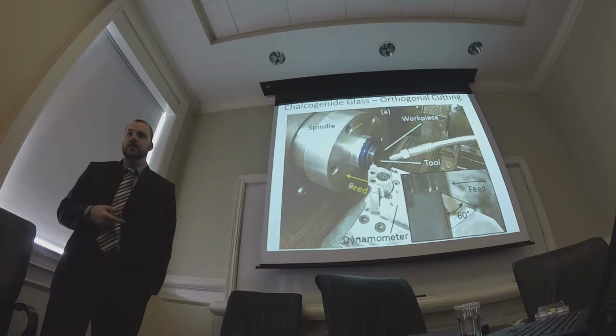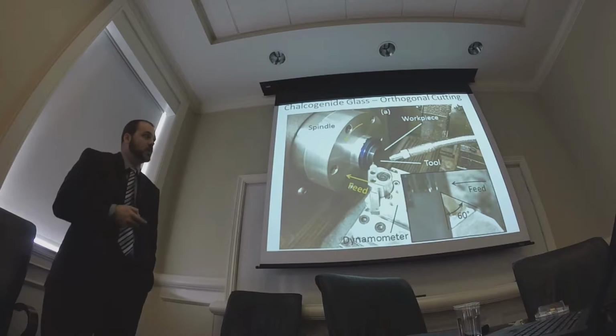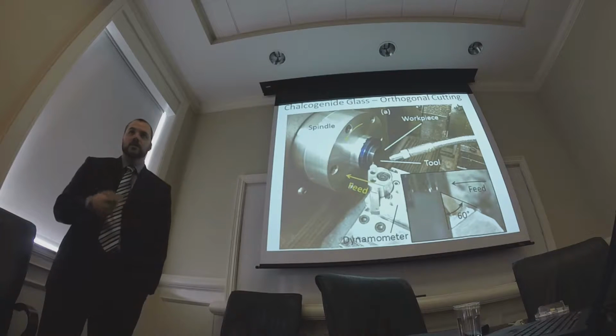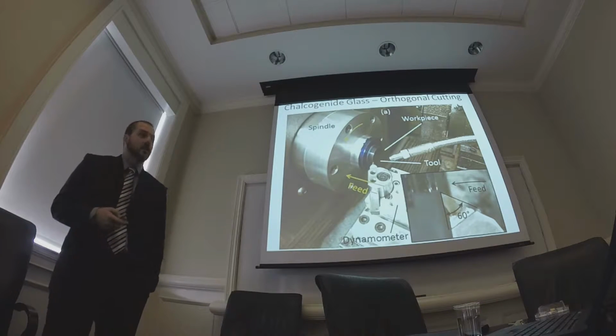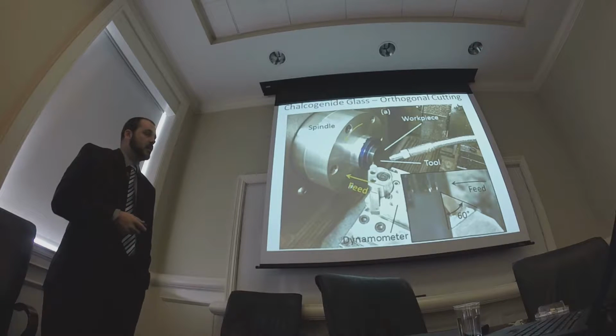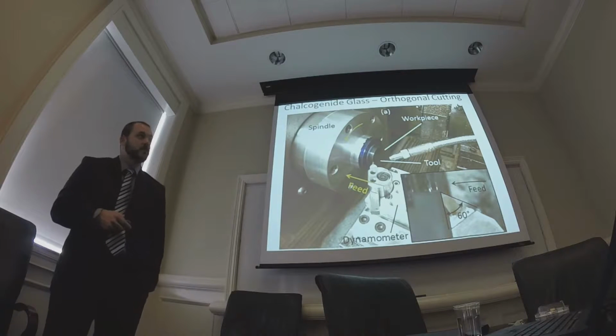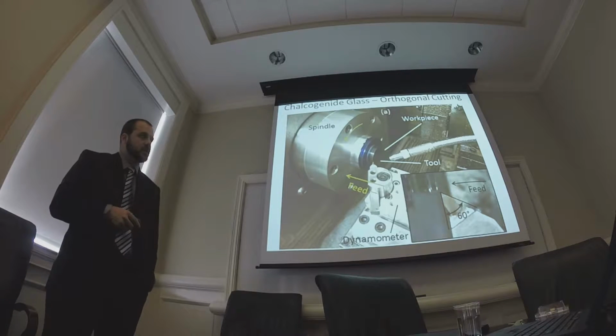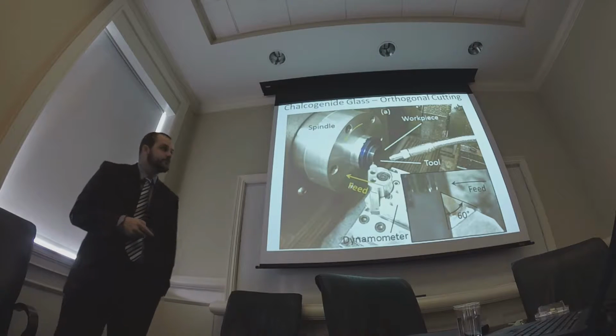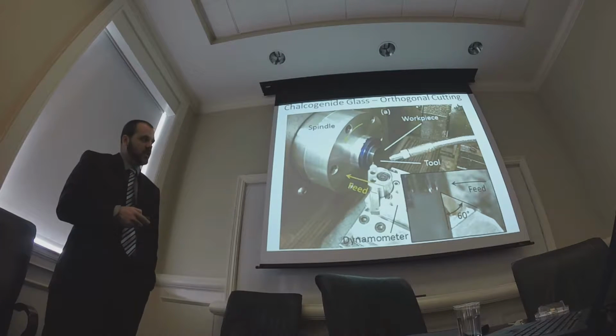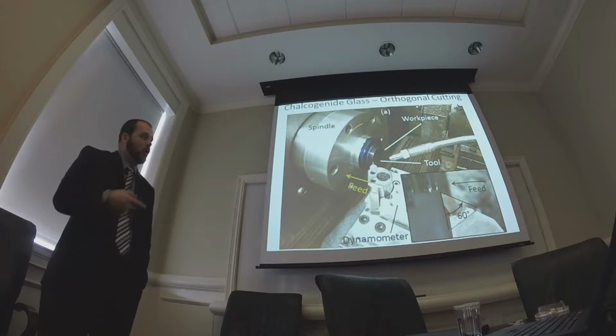We measured them and showed that the forces sideways were less than 1% compared to the other two, or completely covered by the noise. So we've got a dynamometer for measuring the force. We used a 60-degree dead sharp tool, rotated so that the front of the tool, the leading edge, is flat and perpendicular to the feed direction.